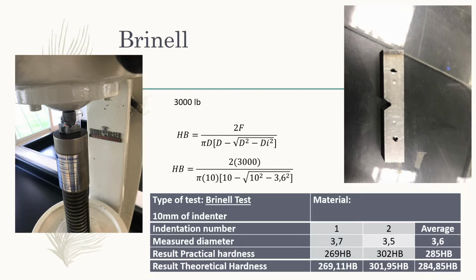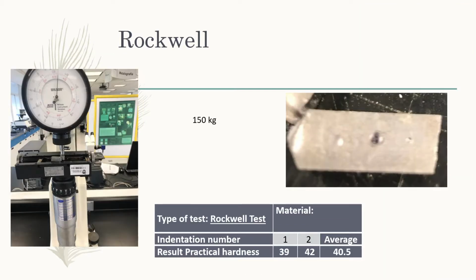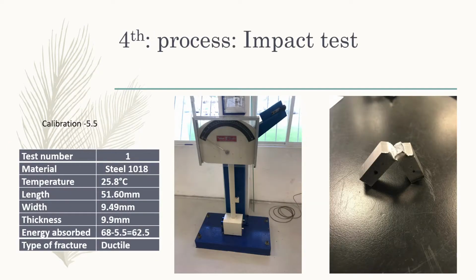Next is the Brinell. So we do it 2 times also and we get an average diameter of 3.6 and a practical hardness of 285 HB. And the theoretical result was 284, so we are not so great. For the Rockwell, we use 150 kilograms and we do it both times and we get an average of 40.5 HRC.